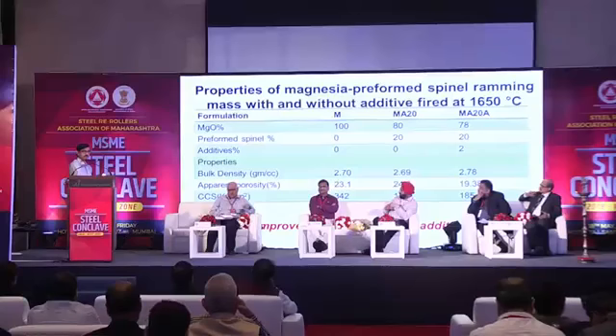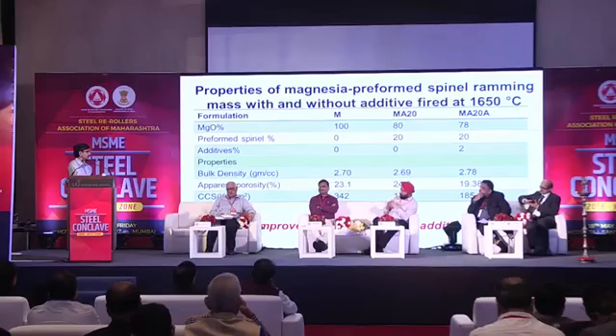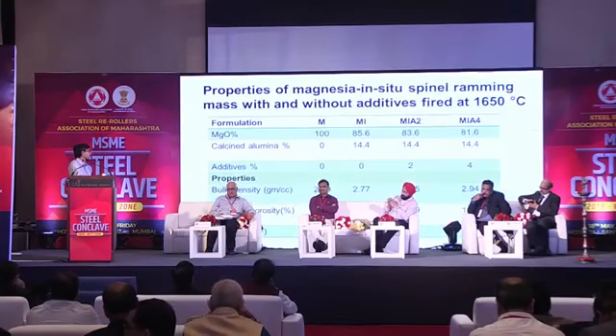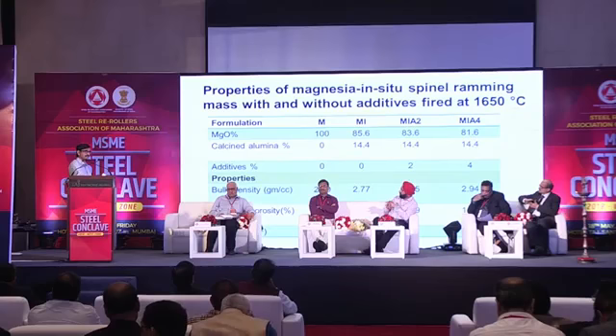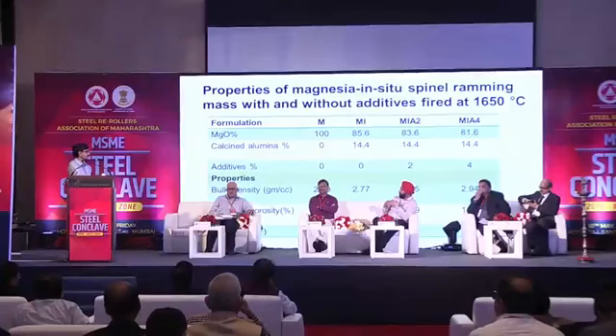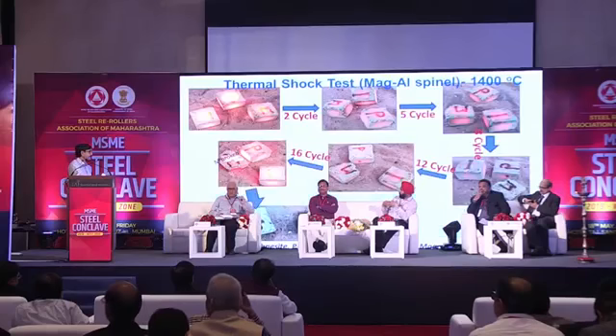And we found out that 20% spinel may be the optimum for this type of work. So 80% magnesite and 20% spinel may give you the optimum result. And then we have tried the in situ also, that instead of pure preformed spinel, we use in situ spinel with some binder. If you use the binder to densify the material and give better strength, then in another way it will decrease the thermomechanical properties or the load bearing capacity. So we optimized the binder also.